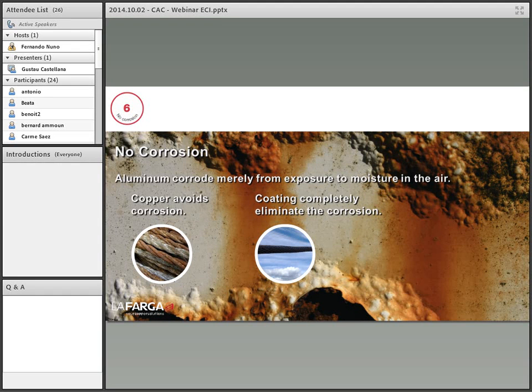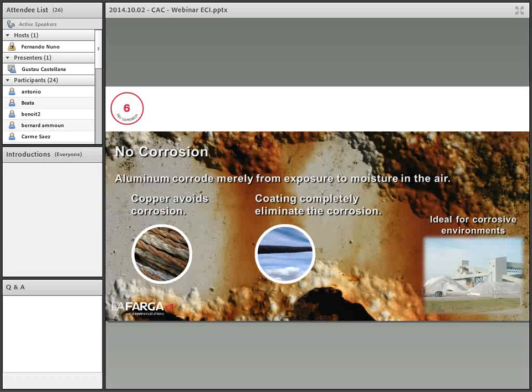So in extreme corrosion or a corrosive atmosphere, copper will behave a lot better and will take more time to corrode. If we add this coating, we completely or almost completely eliminate the corrosion. That makes this solution ideal for corrosive environments. In fact, we have a project with Endesa where we are going to install a CAC conductor, a copper microalloy, in the salt mines here in Spain.